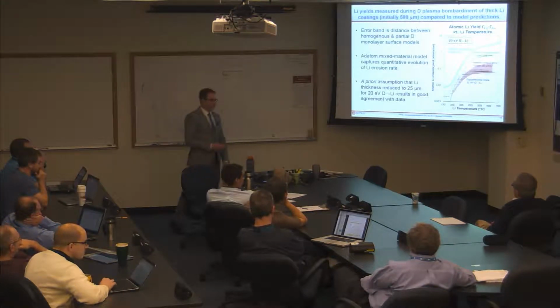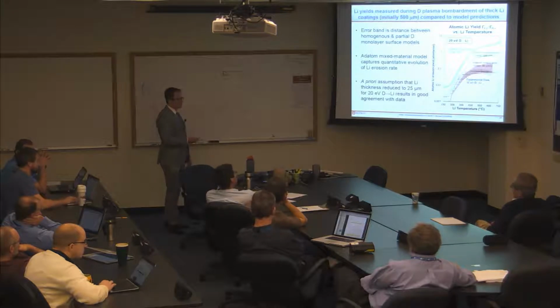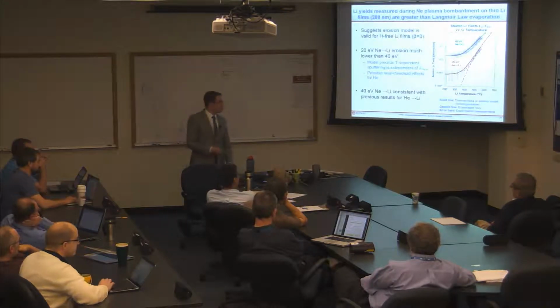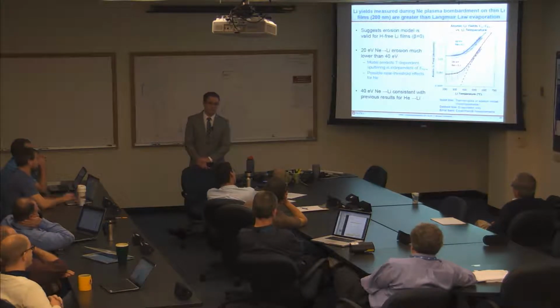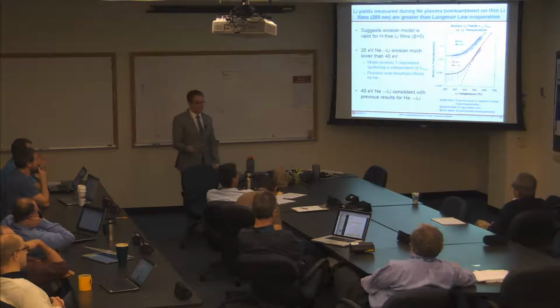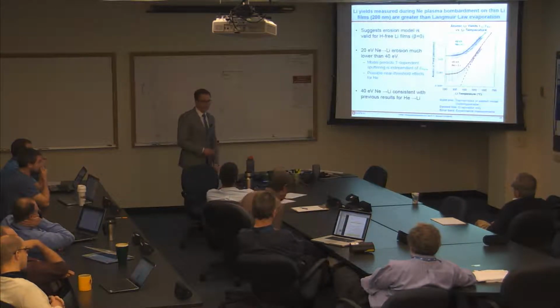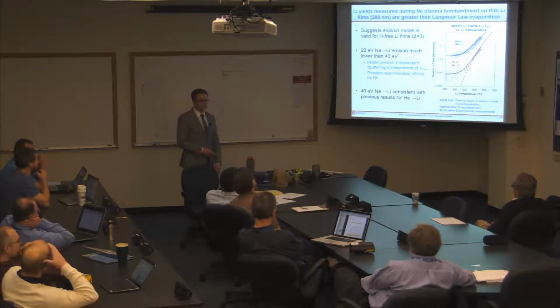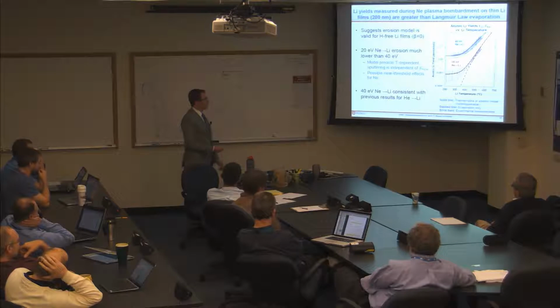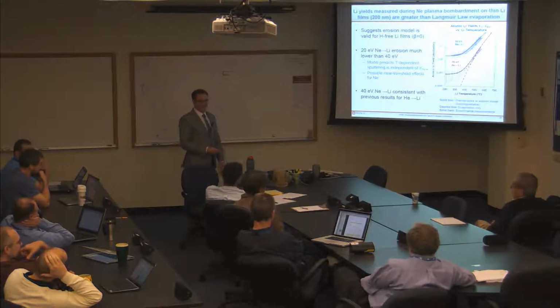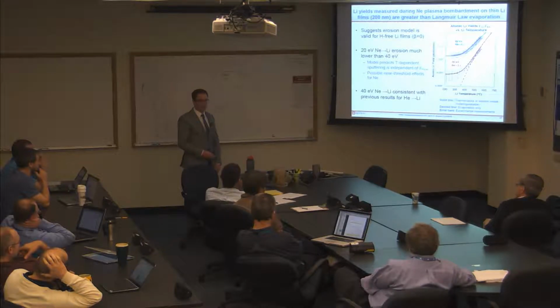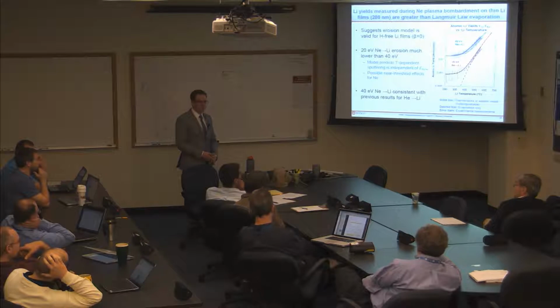Okay, so what about the results for deuterium on lithium? What do you conclude from that? For the red one, you could say it looks like the addition of these two effects, and that's that. Can you do that with the blue one too? Well, you also expect there to be a thermal sputtering term as well, and that's the unknown that I was talking about that we can't really compare with any past experiments. Neon bombardment can induce the generation of atoms as well. It's not a phenomenon unique to deuterium.